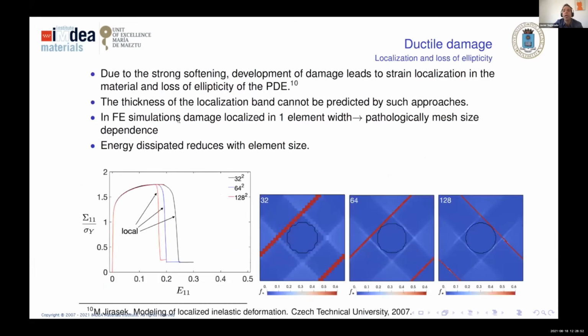The problem of these continuum damage mechanics models, very well known for many years, is that when we implement and try to solve them, at the point where we reach the maximum, we reach a condition of instability. We lose the ellipticity of the governing PDE, and then the deformation starts to localize. Localization is not the problem. The problem is that localization numerically occurs in one element or one voxel, and it is absolutely dependent on the mesh size. This can be seen here.